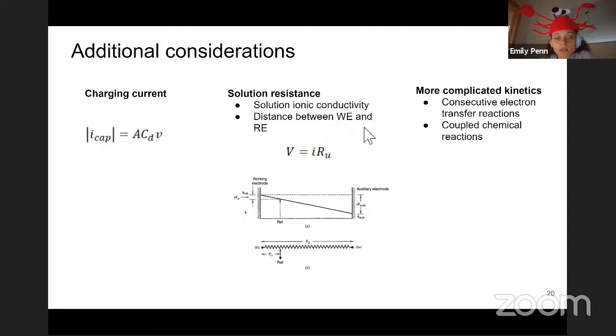Another thing to note is the solution resistance. When you add salt to the solution, you have some ionic conductivity, but if the ionic conductivity is low, then you could still have a lot of solution resistance.